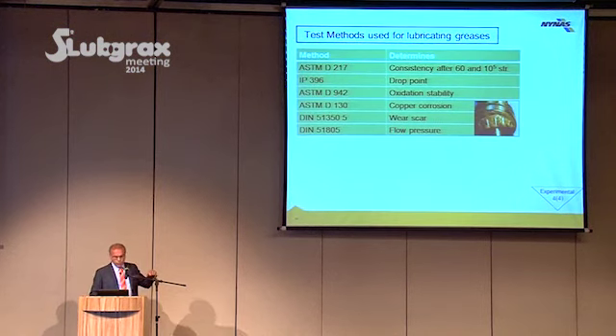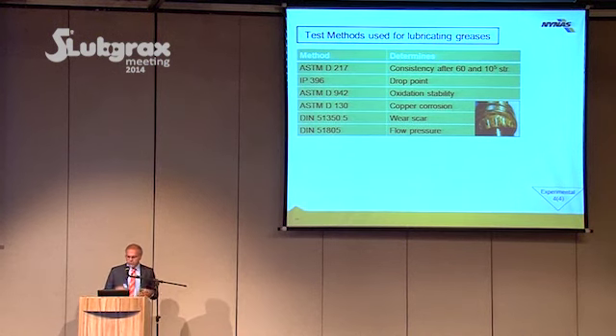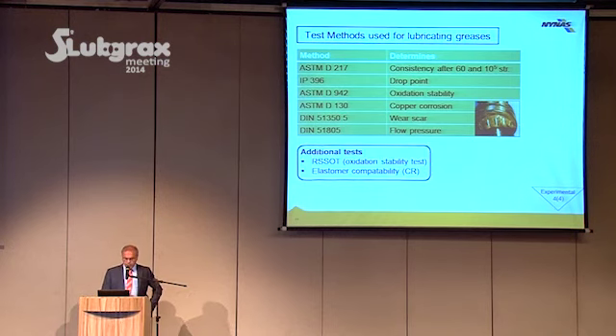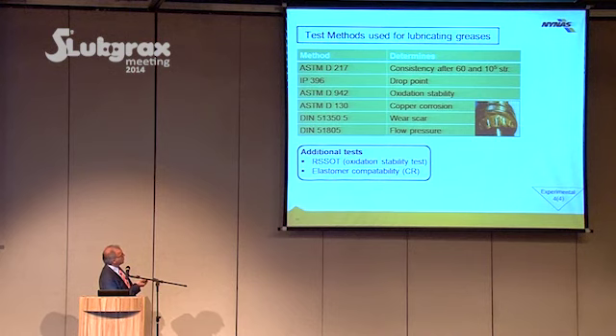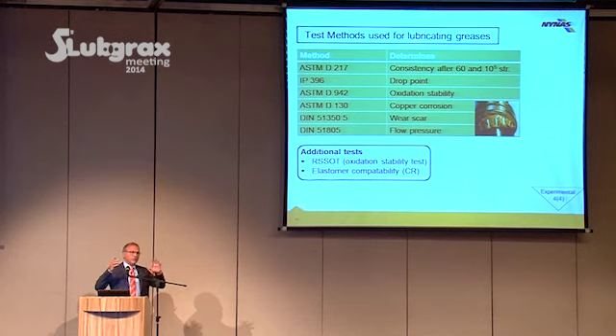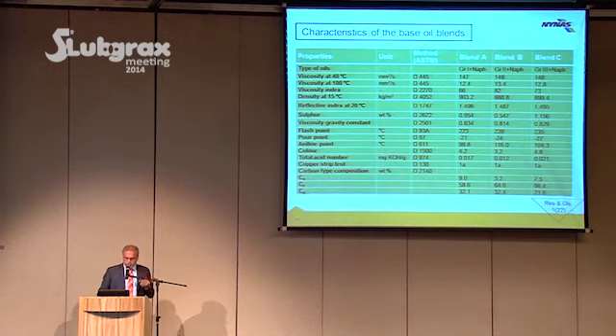When it comes to greases, we did these characterizations. I won't go through them. These are typical: consistency, dropping point, oxidation stability, and so on. But on top of that, we have carried out elastomer compatibility and a new test method which was introduced just 3 months ago in Europe. It's a kind of response to oxidation, and you measure in a pressurized system. I will go into that later on. But what you measure is the induction time. All right. These are the blends.